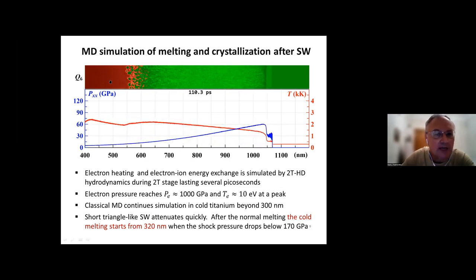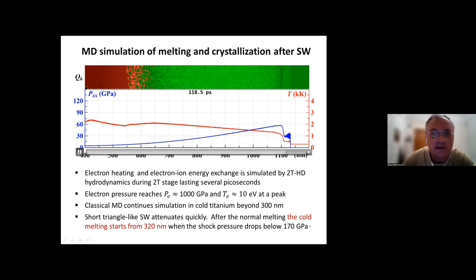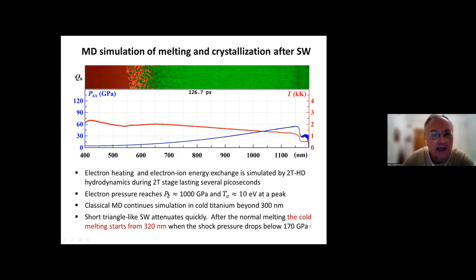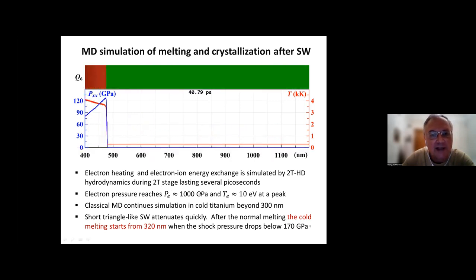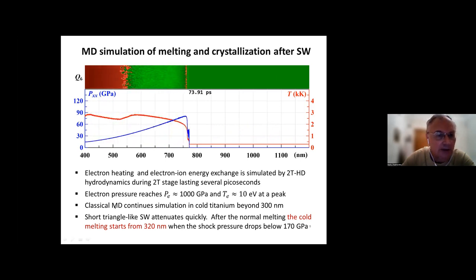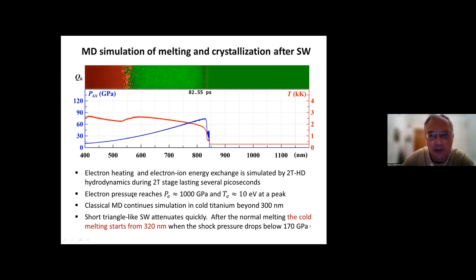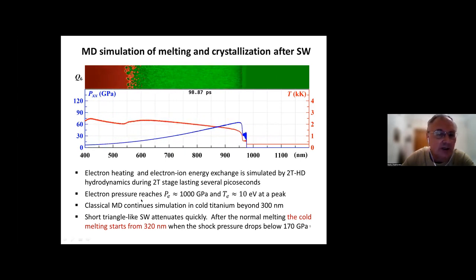I have to say that in the very thin skin layer, a very high pressure, 1 terapascal of electron pressure, was formed with an electron temperature of about 10 eV. Of course, as I said already, classical MD cannot be directly applied to such warm dense conditions.